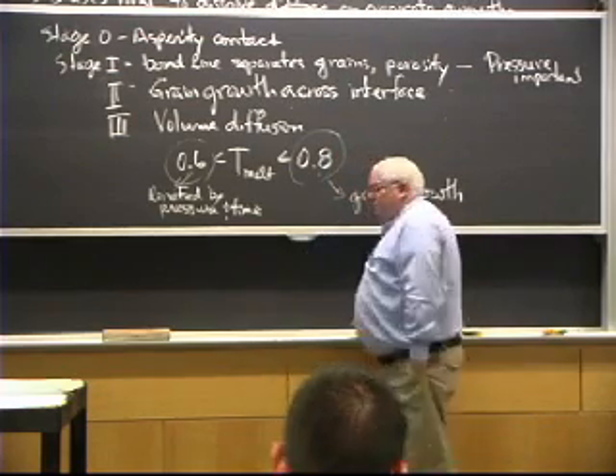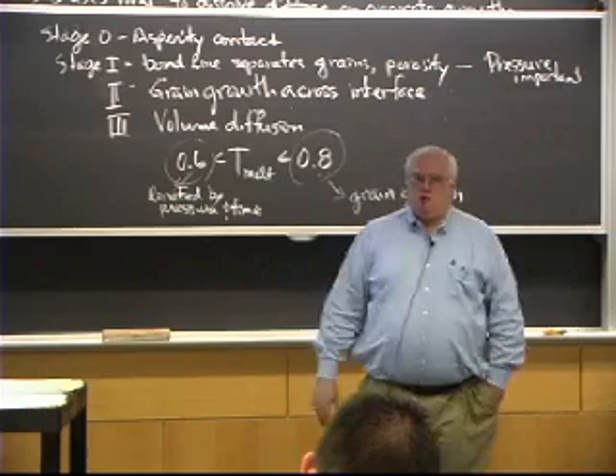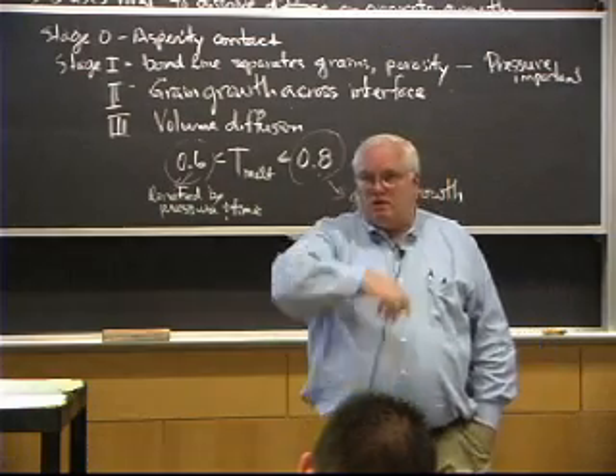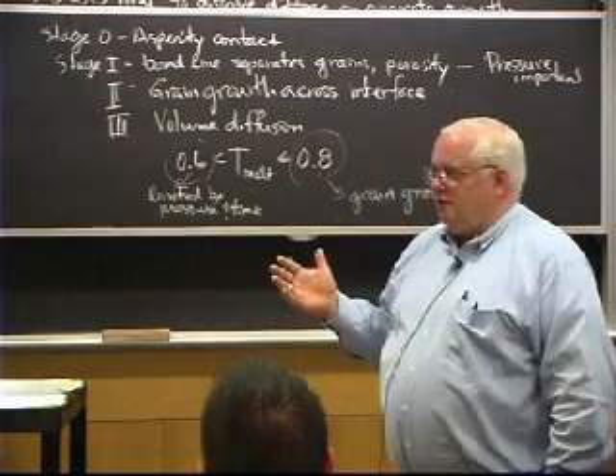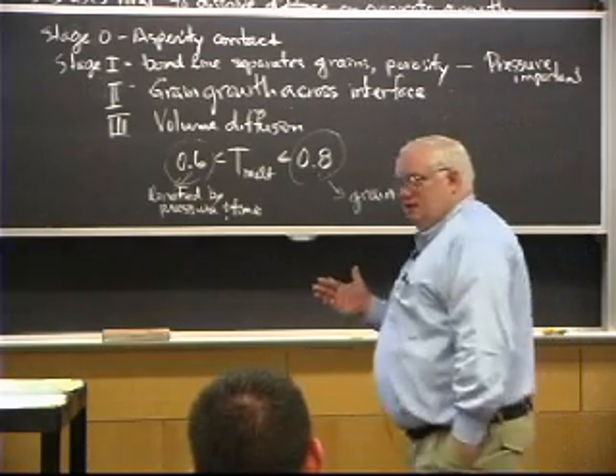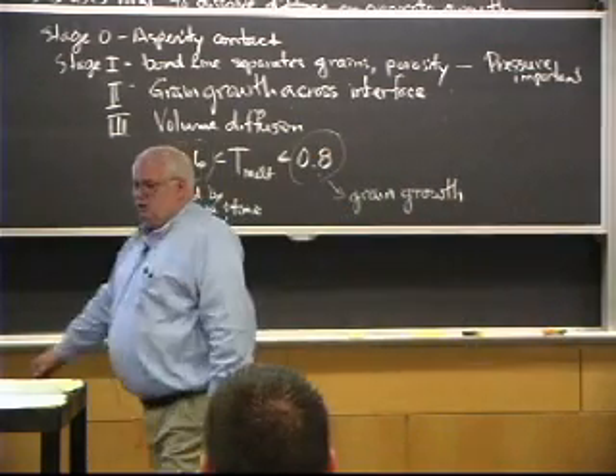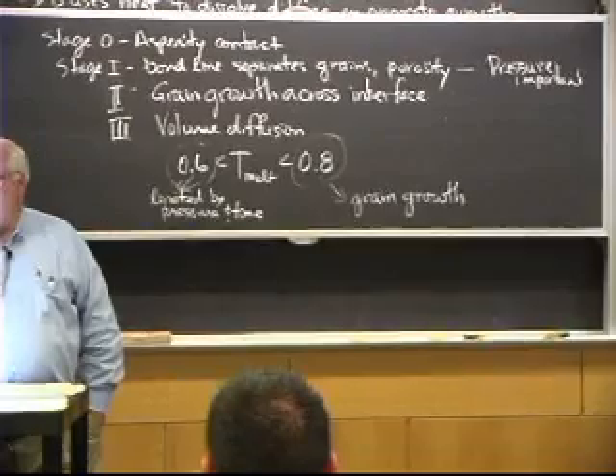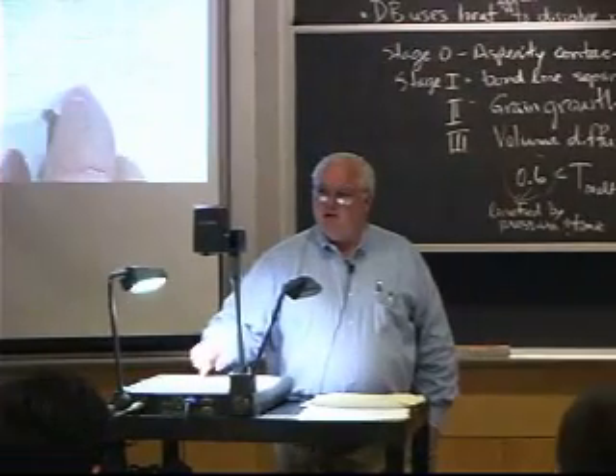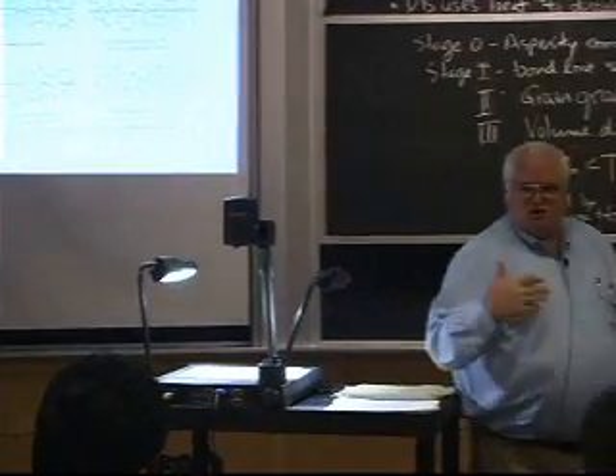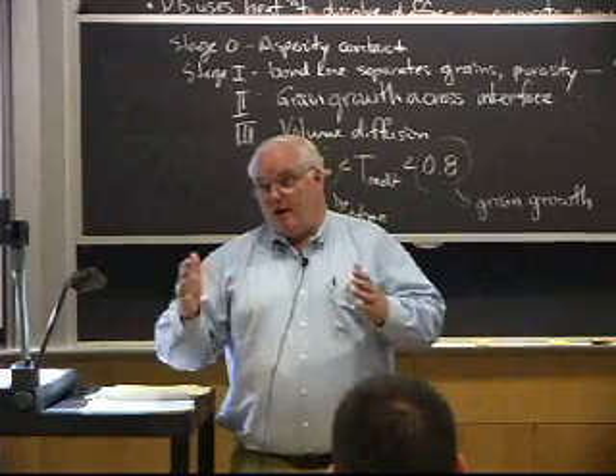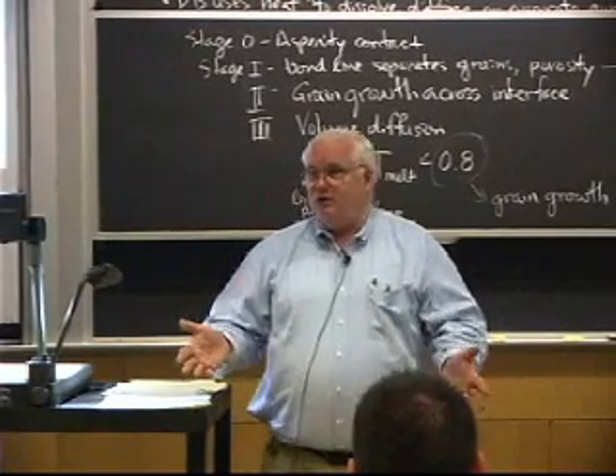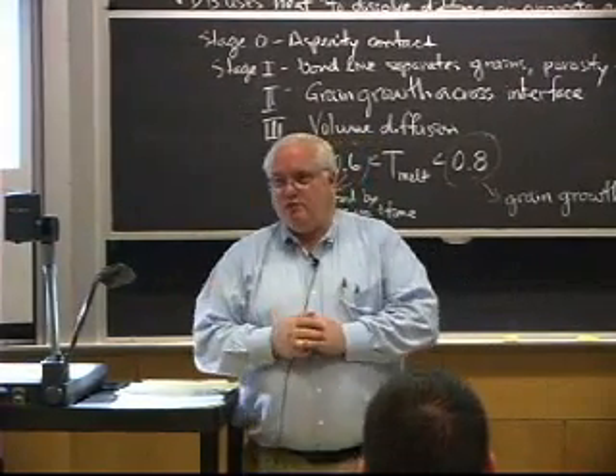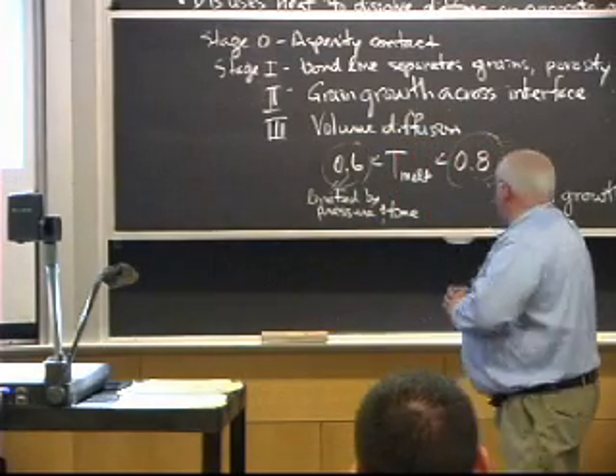Once I get to stage 3, the process is over for all intents and purposes. To get rid of that porosity, it'll take you 10 years for a heat treatment in stage 3, because you're talking about diffusion over hundreds, if not thousands, of lattice spaces as opposed to 2 or 3 lattice spaces. And the diffusion time goes up as the square of the diffusion distance. So if I go up by a factor of 1,000 in distance, I go up by a factor of 1,000,000 in time. Well, I don't want to do it for 1,000,000 hours, okay? I don't even want to do it for 1,000 hours.